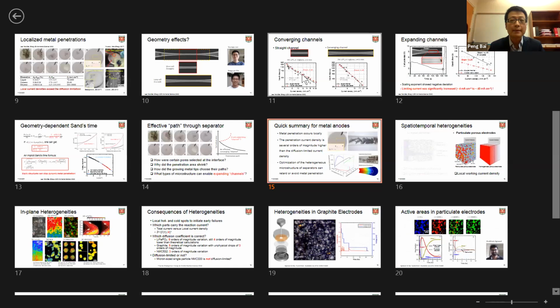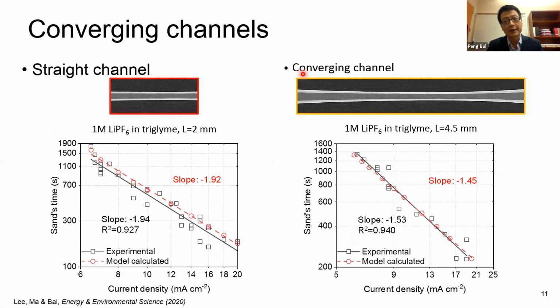Yes, definitely. So let me go back to this result. Basically, you can see here that we have two types of channels. The reason we use a channel instead of some more realistic setup is because you really don't have another more reliable method to probe this problem. And this is the first thing, just to talk about the geometric effect. So here, if we have a straight channel, that means you don't have a geometric variation along your penetration path. Then you get something ideal,